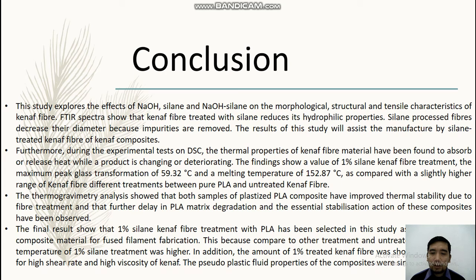The findings showed a value of 1% silane Kenaf fiber treated, the maximum peak glass transition of 59.32 degrees Celsius and the melting temperature is 152.87 degrees Celsius, as compared to slightly higher the range of Kenaf fiber different treatment between pure PLA and untreated Kenaf fiber. Okay, the thermogravimetry analysis shows that both samples of plastic PLA composite have improved their stability due to fiber treatment, and that further delay in PLA matrix degradation and the essential stabilization action of the composite has been observed. Okay, the final result shows that 1% silane Kenaf fiber treatment with PLA has been developed in the study.